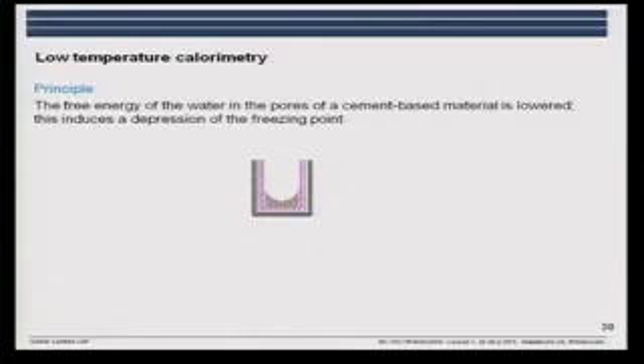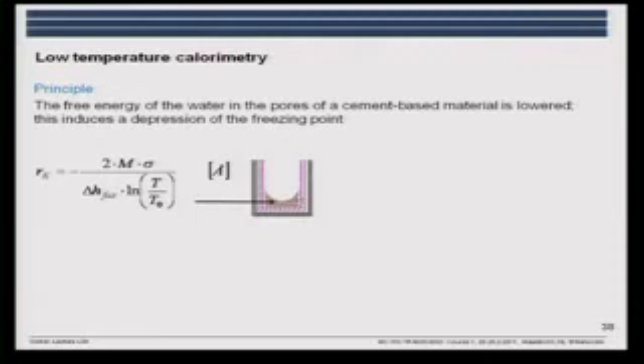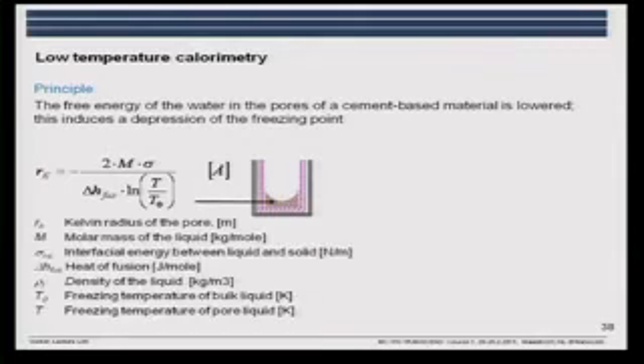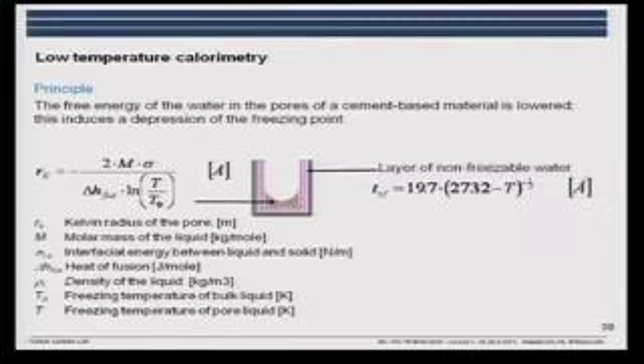Here we have a pore, and this part is the pore wall. Here we have the adsorbed water, and here we have the condensed water. For the condensed water, the size of the meniscus we can obtain from the Gibbs-Thomson equation, where you have all the parameters: the radius of the meniscus, the molecular mass, the surface energy, the heat of fusion, and the temperature difference between the freezing point in bulk and the actual freezing point which we are measuring. And the thickness of the adsorbed layer is a function of the temperature.